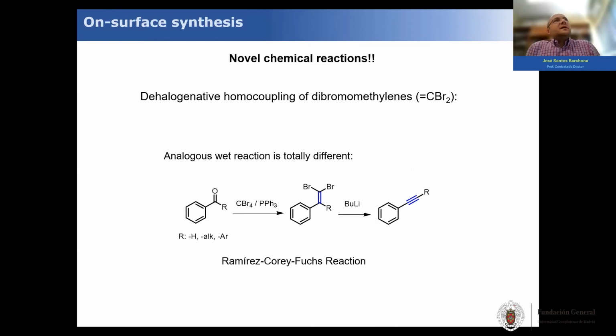Longer polymers. Well, as far as I know, our polymers are already about, correct me if I'm wrong, David, because you're also quite familiar, around 100 nanometers, which is quite long. I think the main limitation is that the termination of our polymers starts when certain hydrogen atoms, which are always present on top of the metal, find one of the ends of our propagating polymer, and then they passivate it and detach it from the surface. So perhaps if we completely removed the hydrogen, we may get extremely long polymers, but I am not so sure you can completely remove the hydrogen.